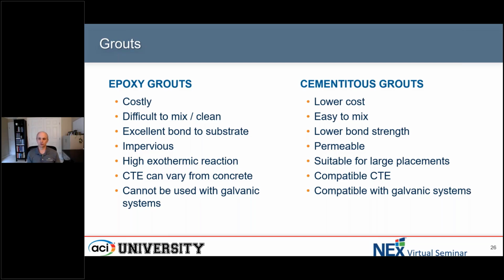Epoxy grouts do have a CTE that can vary from the base concrete, so they do have to have some filler. Usually in the case of epoxy grouts, you're just talking about a sand as a filler. The fillers are used to help match the CTE more closely to the concrete. But again, the fillers need to be used in the proper ratio, and these can then become more difficult to mix in place. So there can be challenges with matching the coefficient of thermal expansion of the concrete itself.